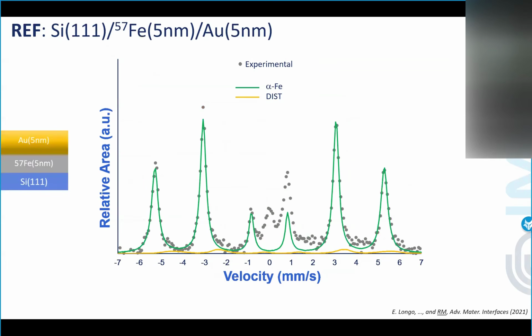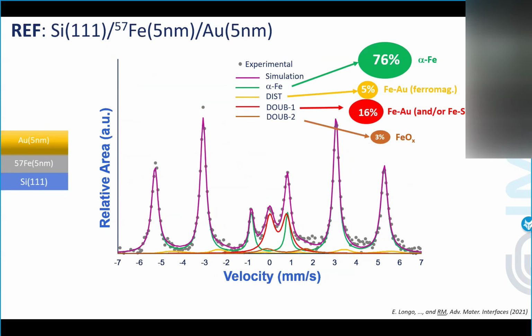We start with a reference sample. We were quite happy with this process. After very few trials, we have been able to produce quite a pure iron layer with some mixing coming with it, from the interaction of the iron with the top gold, and possibly some silicon, some silicide formation, which is quite well known.